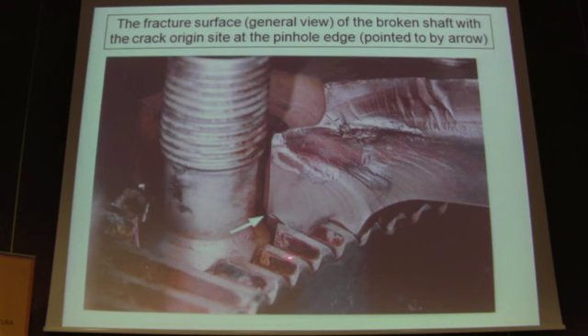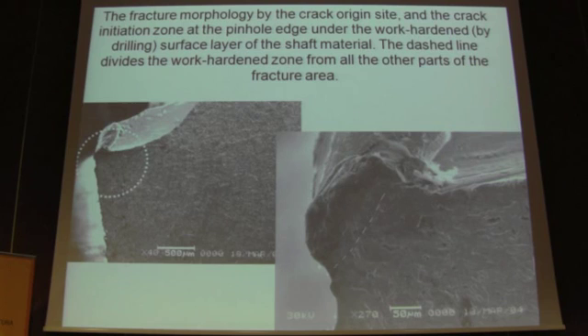Very huge fretting damage, you can see. But cracks start from the corner. Absolutely another situation. The same technology, the same manufacturing procedure, the same connection, but we can see at the corner there is some hardened material because of something wrong in the corner repairing. You can see this material. And the crack starts because there are residual stresses which influence the crack start.